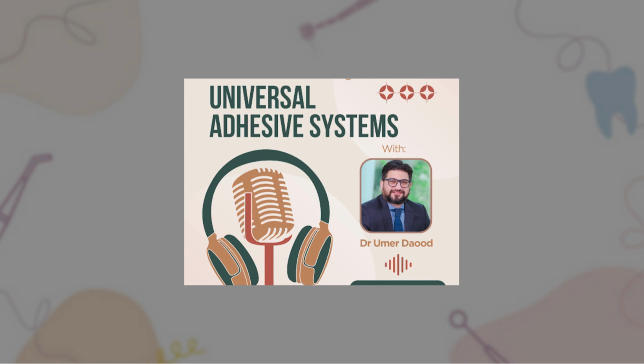These polymerized and unpolymerized hydrophilic monomers present within the adhesive are always vulnerable to degradation. So in order to compensate for that, ethanol wet bonding was introduced. It uses ethanol as a solvent to dehydrate the demineralized dentin matrices and to assist the infiltration of more hydrophobic monomers inside the dentin.